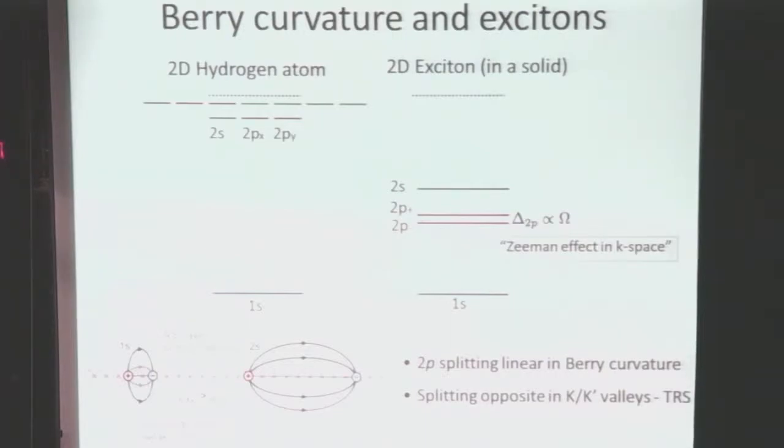And this has been predicted for at least the last 5 years, and this results in the Coulomb interaction being describable with a logarithmic function, and results in this deviation from the hydrogenic spectrum. So the n=2 manifold, for example, has a much stronger binding because of the reduced screening as compared to the n=1 manifold. But that's not what I would like to draw your attention to.